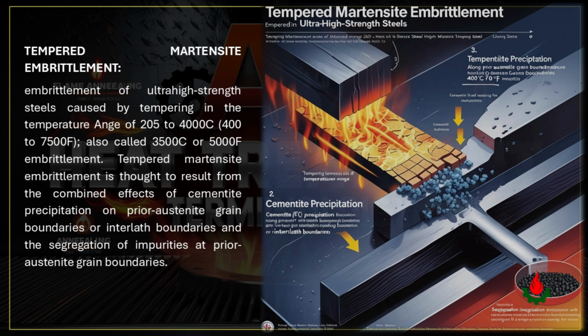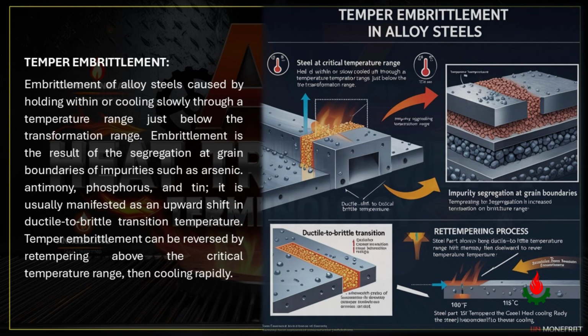Tempered martensite embrittlement. Embrittlement of ultra-high-strength steels caused by tempering in the temperature range of 205 to 400 degrees Celsius, 400 to 750 degrees Fahrenheit, also called 350 degrees Celsius, or 500 degrees Fahrenheit embrittlement. Tempered martensite embrittlement is thought to result from the combined effects of cementite precipitation on prior austenite grain boundaries, or interlath boundaries, and the segregation of impurities at prior austenite grain boundaries.